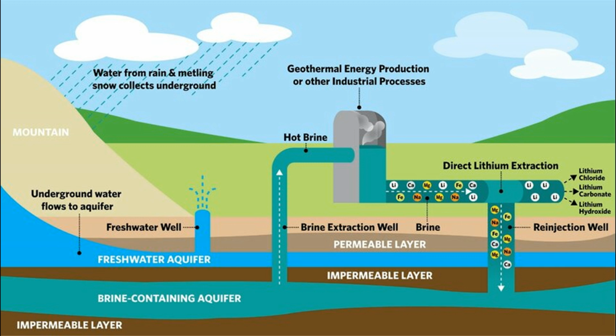The brine that results from these chemical precipitations is then subjected to a carbonation process, where the lithium reacts with sodium carbonate at 80–90 degrees C to produce technical-grade lithium carbonate. This can be further purified to produce battery-grade lithium by redissolving the lithium carbonate, and then using an ion exchange process to remove impurities. To reduce the time that is required for solar evaporation concentration, lithium will sometimes be precipitated as lithium phosphate, which precipitates more quickly than lithium carbonate due to its roughly 30-fold lower solubility. Lithium phosphate is then converted into battery-grade lithium hydroxide through an electrochemical process.